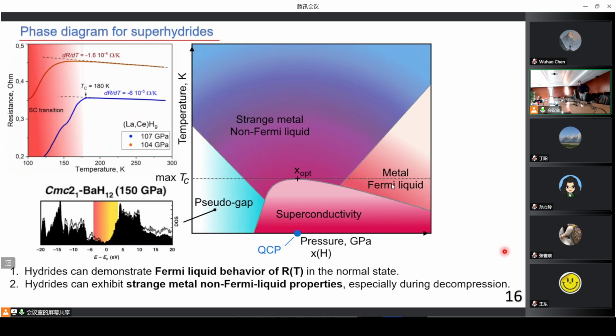And we can even propose a qualitative phase diagram for hydrides, which is very similar to the phase diagram proposed for cuprates. We can also observe several regions here. Definitely hydrides may demonstrate Fermi-liquid, metal-like behavior in normal states. There are no doubts about that. But they may also demonstrate strange metal, non-Fermi liquid behavior. And as you saw, pseudogap behavior with a negative first derivative of resistance. And of course, the superconductivity region is also here.